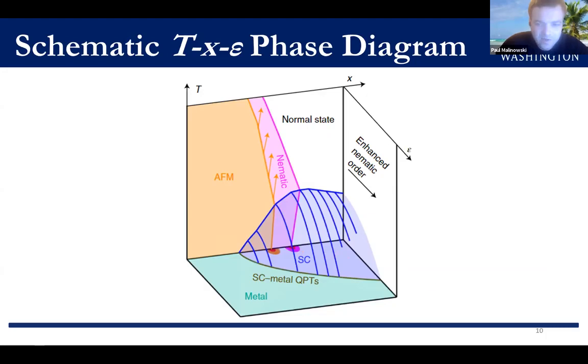So this is what makes the huge sensitivity near optimal doping so intriguing, because as I mentioned, in that case, we are outside the magnetic phase. We expect to be increasing the strength of spin fluctuations, and yet we still see the superconducting state weaken considerably. So perhaps it really is the nematic fluctuations that are important for producing a high TC.